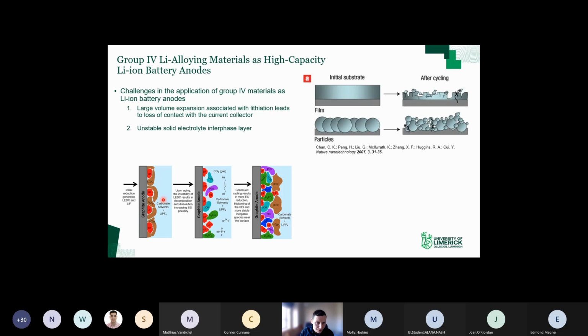But basically the SEI layer forms because of the potentials that lithium-ion batteries operate at, where the electrolyte is unstable. So in the first cycle or the first initial cycles, you get decomposition of the electrolyte at the surface of the graphite anode, and this happens with silicon as well. That is actually beneficial in a graphite anode because it passivates the surface of the anode, but it's not beneficial in a silicon electrode because it's unstable. So you get continuous decomposition of the electrolyte with every cycle. That's something that does need to be overcome if you want to cycle silicon or germanium for thousands of cycles.